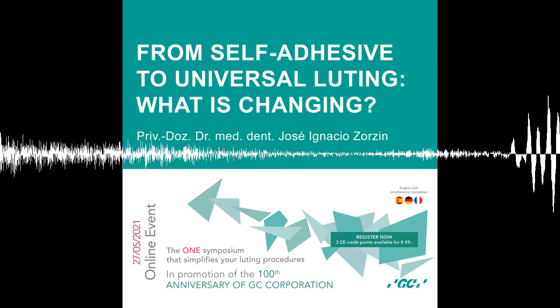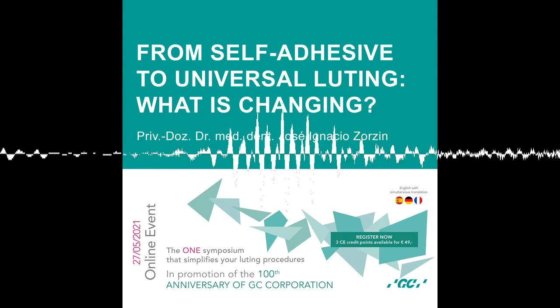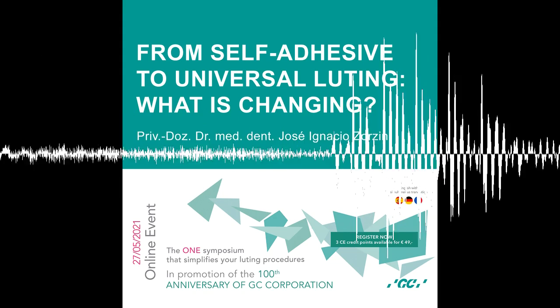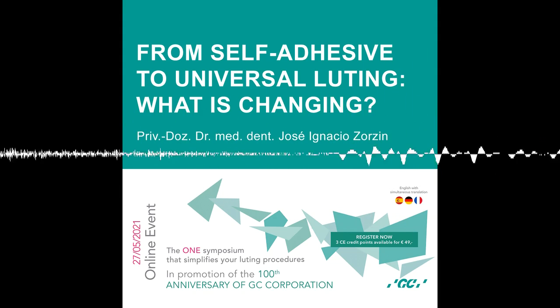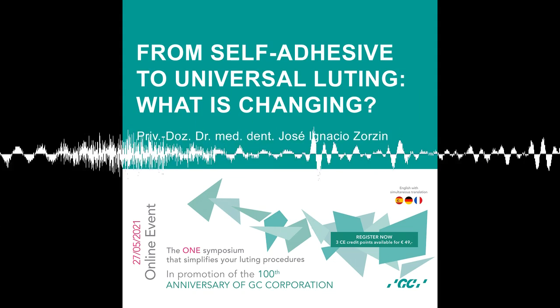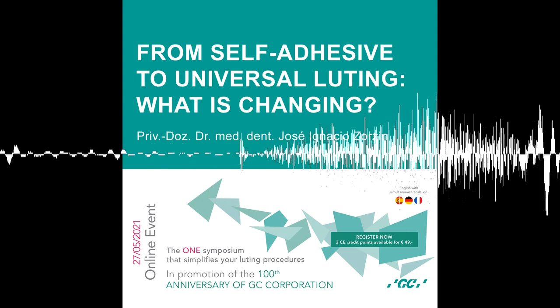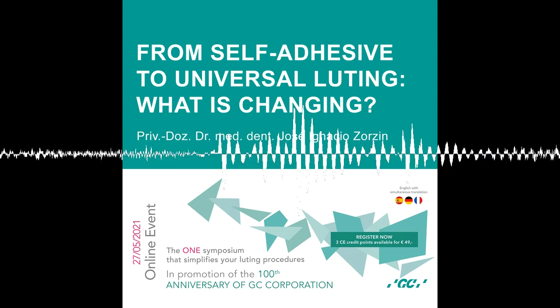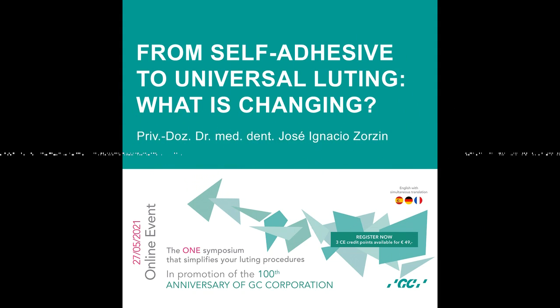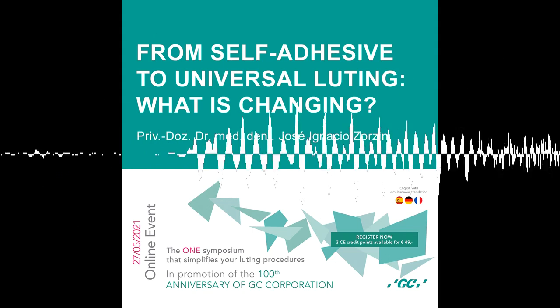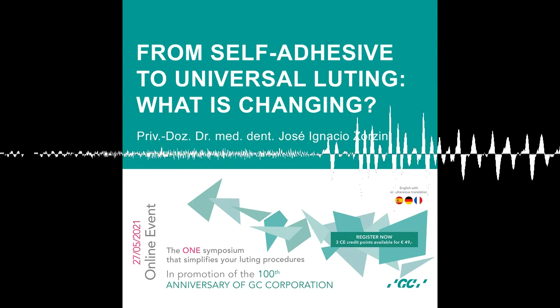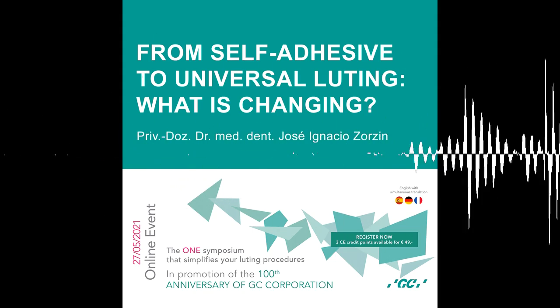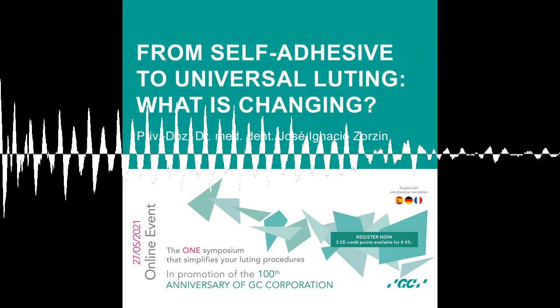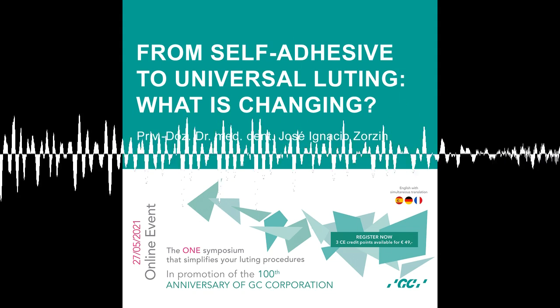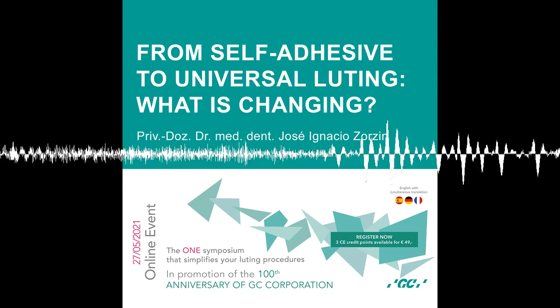Okay. Yeah, we can still talk a lot about pretreatment of the different indirect restoration substrates, for example. That's also an interesting point. What's the point you find most interesting in the pretreatment? First of all, it's important to have clean surfaces. Sometimes I see that colleagues just say, okay, my dental technician already pre-treated the surfaces. For example, zirconia, he already did the abrasion, and when you do the try-in, this will get contaminated with saliva, so you have to clean the surfaces properly.